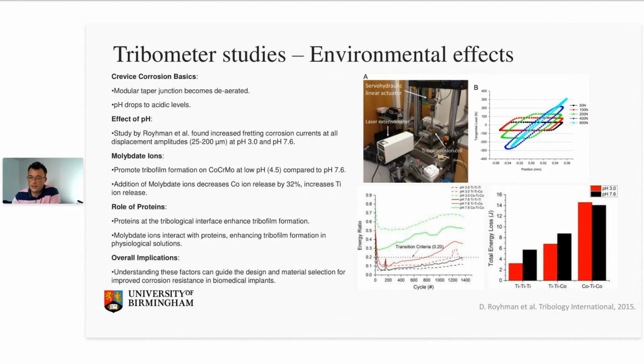But what was particularly interesting within these occluded cells that they developed was the role of liberated ions and how they interact with things like proteins in those interfaces to form these lubricious and protective tribochemical films on the surface. From an academic point of view, these are interesting because they demonstrate this mechanochemical interaction. But from an optimization and translational point of view, it raises again questions as to what the optimal environment is, or how we can engineer these environments to give us optimal conditions within these interfaces. And from a tribological point of view, where we may want low coefficients of friction to facilitate slip within a bearing, for example, in these fretting interfaces it's often that we don't want that. So how do we engineer that, considering fretting as its own unique aspect.